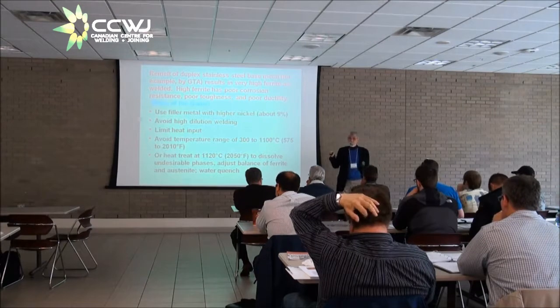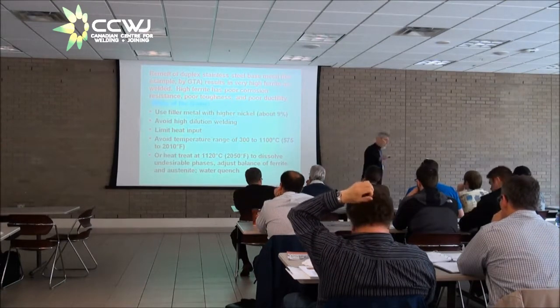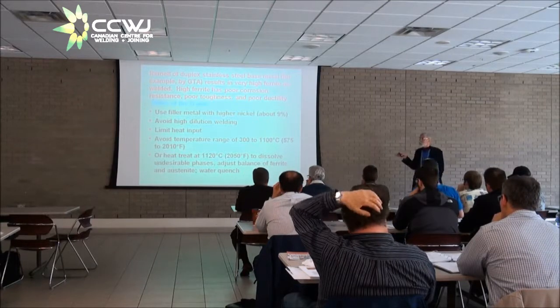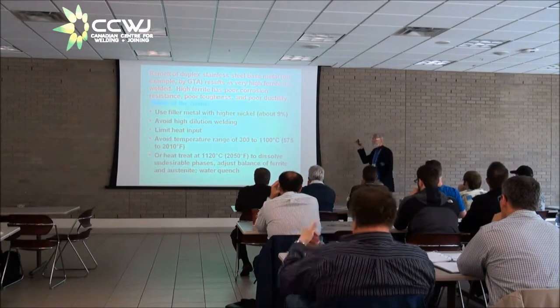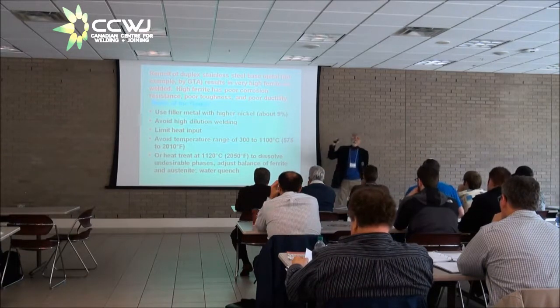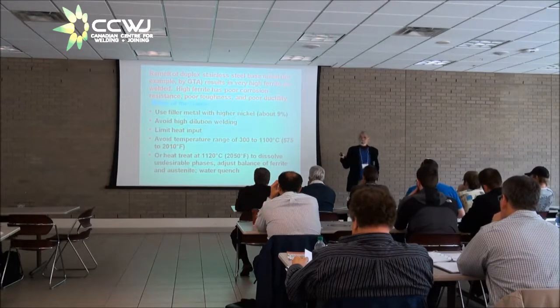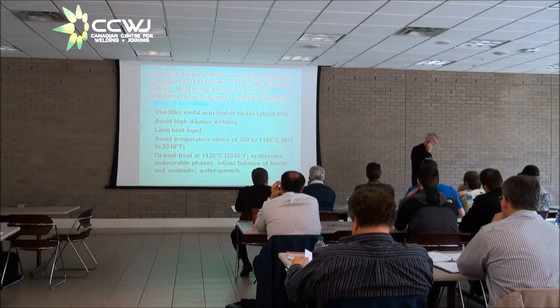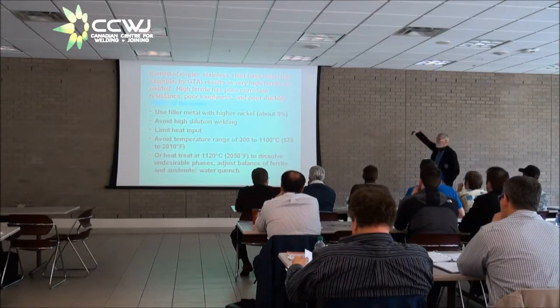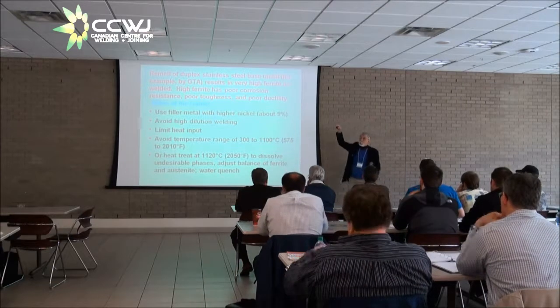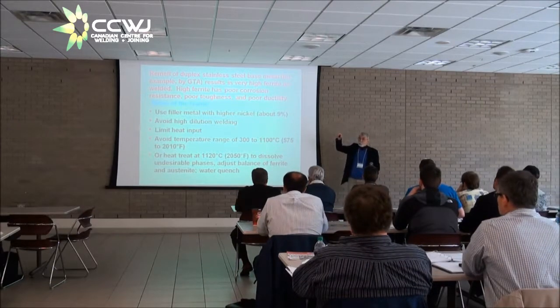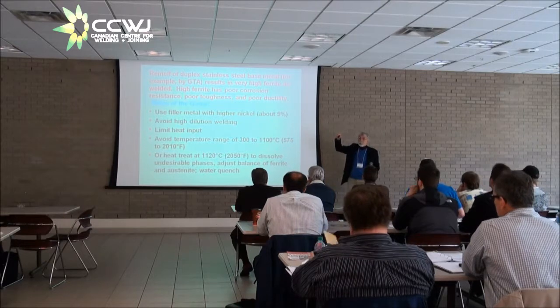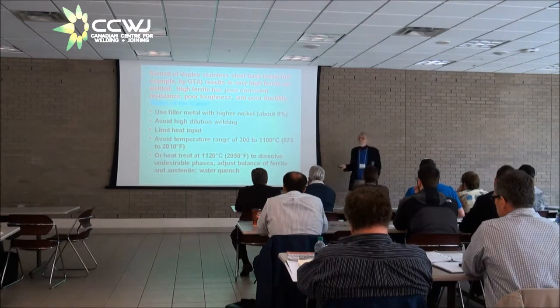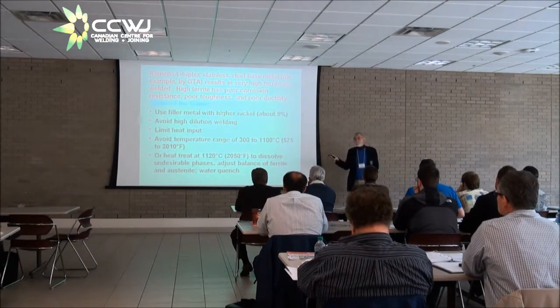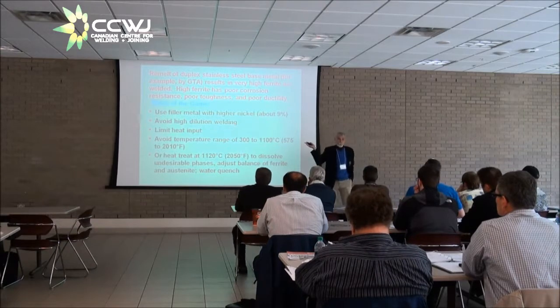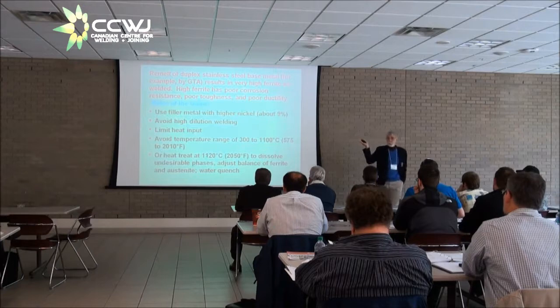Now, the purveyors of the alloy 255 base material have insisted for a long time that annealing had to be done at 1040 degrees. That you shouldn't anneal at a higher temperature because you'll still have some residual nitrogen in the ferrite, and that might cause chromium nitrides. And so one of the things I worked out in my years at McKay was what we call a step anneal, where the initial annealing temperature was 1120, and then we dropped the temperature in the furnace to 1040. Held it at 1040 for only a few minutes, and then yanked it out and let it quench. And then we could get good annealed properties in the Alloy 255 weld metal. And we could follow their recommendations.